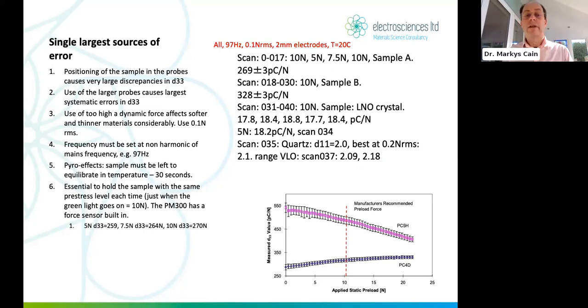So bottom line is, hold it with tweezers. Don't blow on it. Don't get it hot locally. Use tweezers, yeah. And then let it equilibrate for temperature for maybe 5, 10, 30 seconds, something like that, okay? And now, because of course we're modulating at a certain frequency, and you typically will be using lock-in methods, this is less of an effect, okay? Because you're locking into a certain excitation frequency, but still, especially for pyroelectric, for polymer materials, this is a big issue.